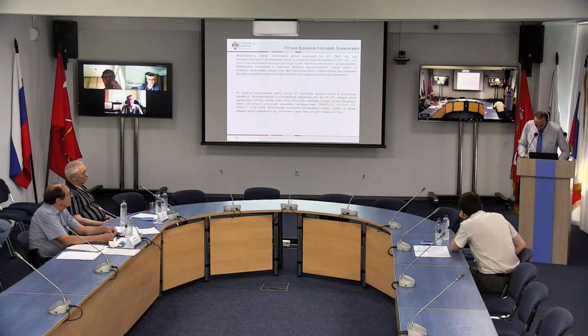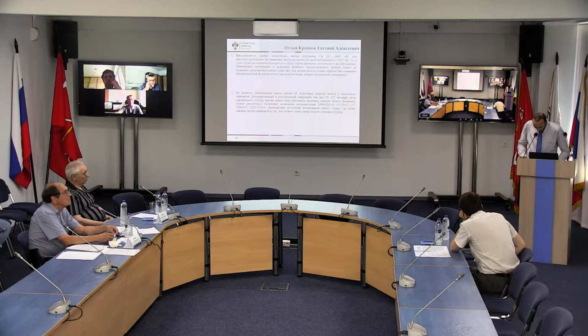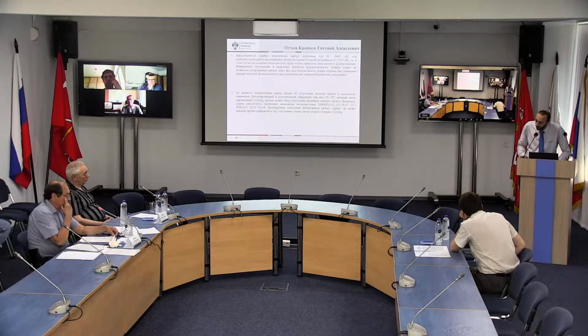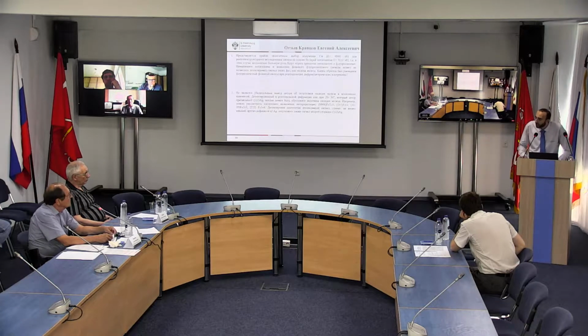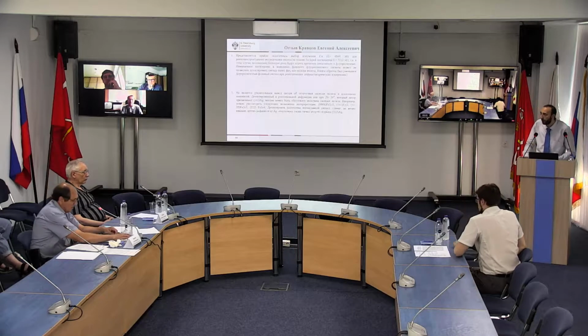Final point, about why there are no other peaks of oxidized ferric iron in the same direction 111. If there are other expected peaks of iron oxides in the 111 direction, they will be covered by the most noticeable alpha iron phase. And about the absence of ferric oxide lines, we expected that, as during synthesis ascorbic acid was used, trying to minimize the concentration of ferric ions in the electrolyte in order to increase its stability toward oxidation by air. So that's all. Thank you.